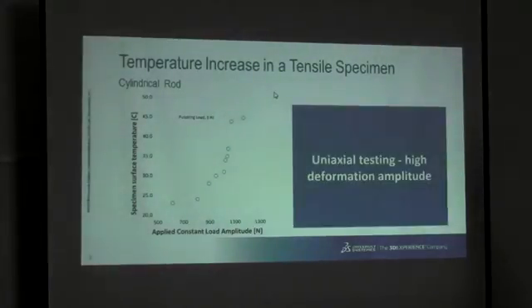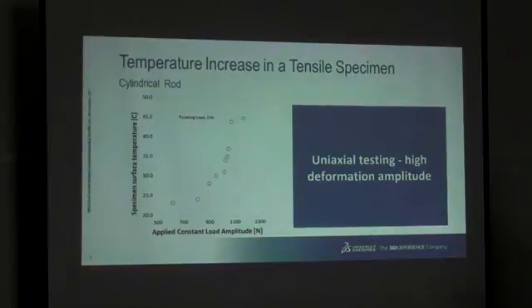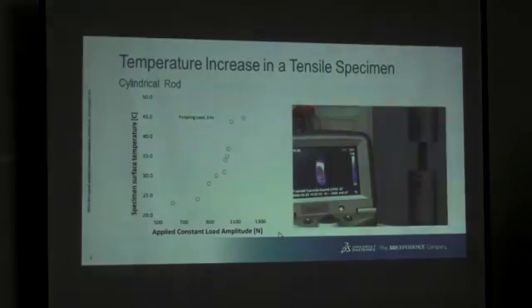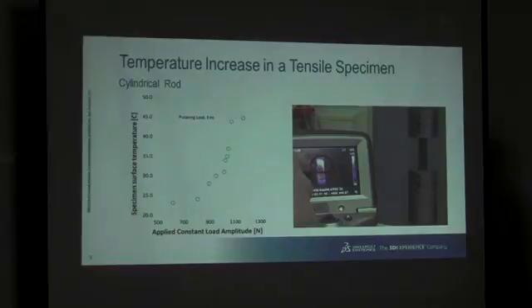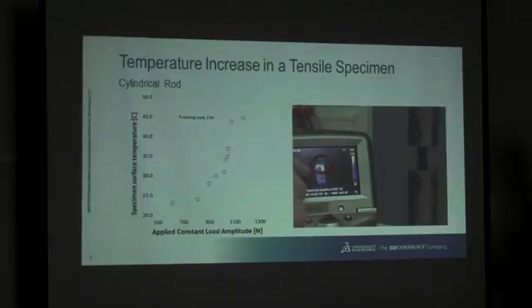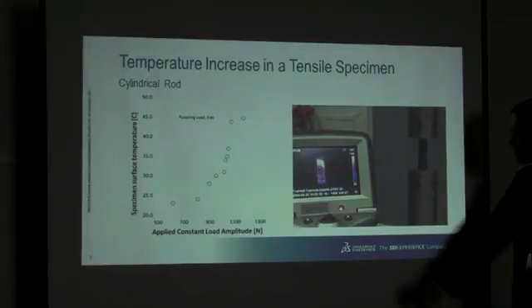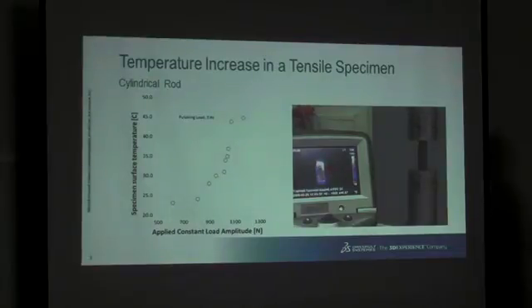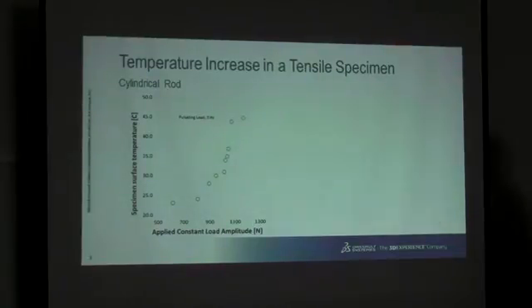So what happens if we now go to a different case where we increase the amplitude? If you want to convert this to strain, instead of displacement, this is an amplitude of plus minus 10%. Let's see if I can get it running. Here we go. Now what's happened to form is that, well, this specimen has been mounted slightly askew, that's why we're seeing a shear band. It's going into, well, almost buckling, but because this is a visco-plastic material, buckling isn't that big a problem. It's more bound by the geometry than it is of the massive bulk. I'd like you to observe this little location where a crack has formed and it closed, and then at some point, boom, we pull it apart.